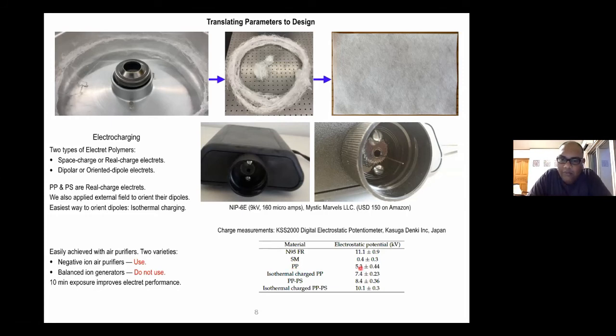The isotactic polypropylene that I manufactured with the cotton candy machine, without the isothermal charging, gave me a potential of 5.3 kilovolts. But after isothermal charging with the system, it jumped up to 7.4. The mixture of polypropylene and polystyrene was higher, and after isothermal charging, it went up to 10 kilovolts. That was the closest I could get to the static charge capacity of the N95 filtration layers. So you can see the last few slides have been more tinkering and engineering than science.